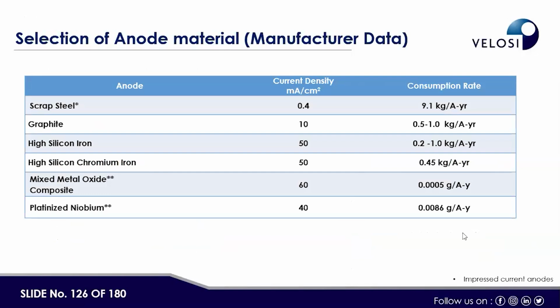We can also use scrap steel, the same old pipe which is in your store, as an anode material, but it will be diminished. It will expire very soon, because for 1 ampere of current, 10 kilograms of the pipe will be consumed. It means you need to replace that anode bed very often and very frequently.